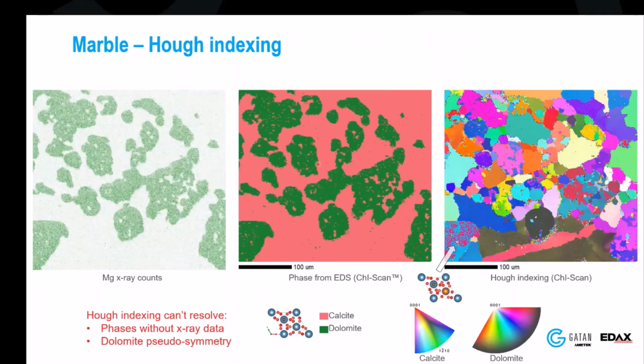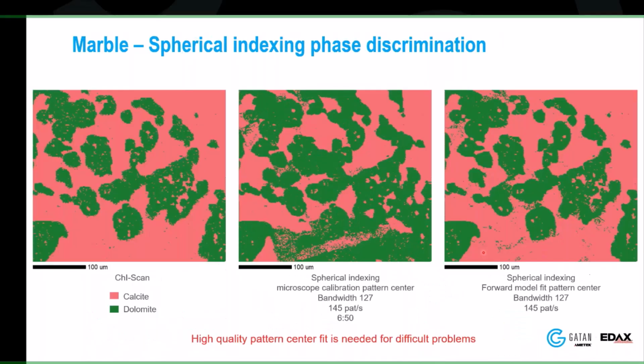If I start looking at the orientation information, I can start to see that I'm having a little bit of difficulty with some materials here. So I can see I'm getting some speckling in some areas because of the pseudosymmetry problem that I can't tell the difference in Hough-based indexing. What happens when we use spherical? Well, here you can see that spherical does a really good job of pulling this apart.